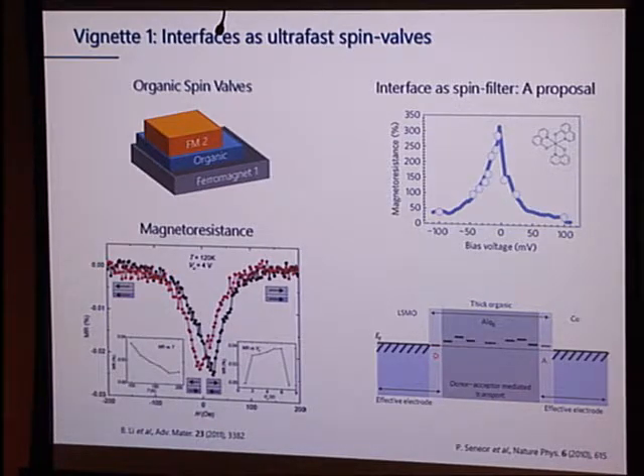And if you want to transport spin, you don't want it to be scrambled through spin orbit coupling, and hyperfine splitting and so on. This is usually a problem when you do this in dilute magnetic semiconductors. That was one of the issues with the spintronic community in the 90s. So this promises to have much longer spin coherence times or lifetimes, which means that you should be able to salvage spin over significant distances and therefore make relatively readily a functional device. This was demonstrated, as I said, about 15 years ago.